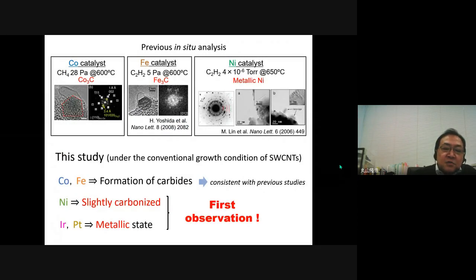So previous in situ TEM analysis showed that cobalt and iron catalysts became carbides. Our results by in situ XAFS analysis under the conventional growth condition were consistent with them. However, we observed nickel catalysts were slightly carbonized under the conventional growth condition. Also, we found that platinum group metal catalysts became metallic during nanotube growth. This is the first observation for platinum group metal catalysts using in situ analysis. Next, please.